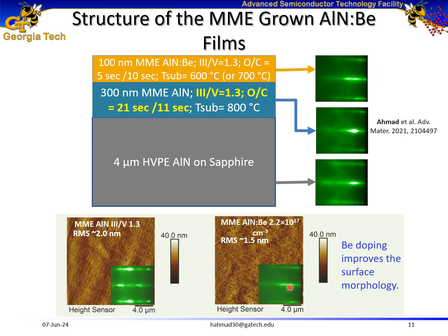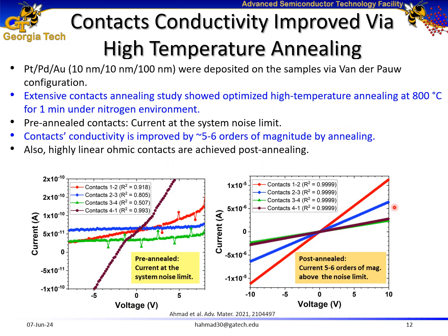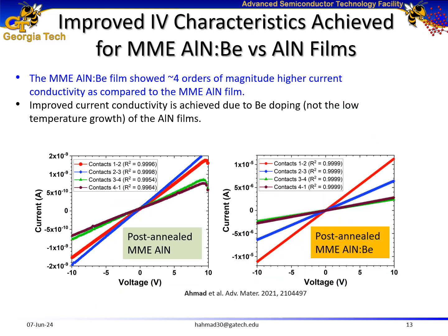From AFM comparison of a beryllium doped aluminum nitride versus undoped control sample, we see that beryllium doping improves the surface morphology. Later, I deposited platinum, palladium, gold contacts on these films for Hall measurements. And from extensive optimization of the contacts, here I've shown a comparison of the post-annealed beryllium doped aluminum nitride versus pre-annealed contacts. And the annealing improves contacts conductivity by approximately 6 orders of magnitude.